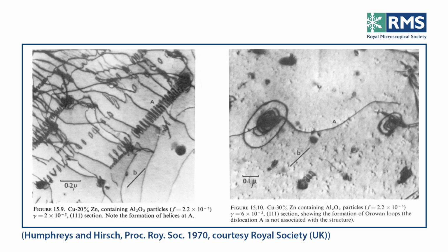Well, then the next slide shows you what structure you get if you have non-deformable particles like oxide particles in the material. You get these complicated dislocation structures, and you can visualize that if you try and force another dislocation through, it will be difficult to do, and that leads to hardening. So that is an example of alloy hardening. The mechanism of alloy hardening can now be understood and studied.